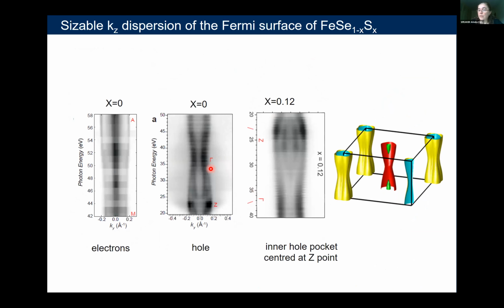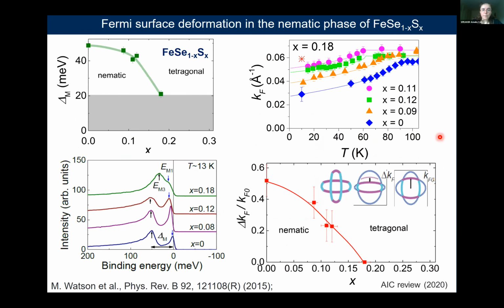But these materials have very strong Kz dispersions, and as you can see, at about 12%, the pocket is recovered, and the Fermi surface of iron selenium at high temperature is recovered as we turn off the effect of nematicity, and we have a Fermi surface containing a hole band, but also a three-dimensional little carrier, which plays a role in transport. So this is the summary of what we see in experiments: the effect of nematicity shifts the bands by about 30 milli-electron volts, and we have a very strong Fermi surface distortion.